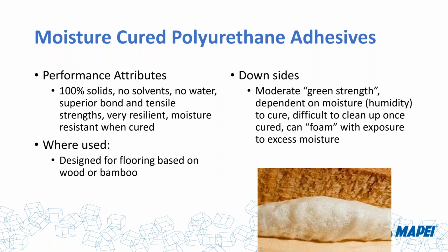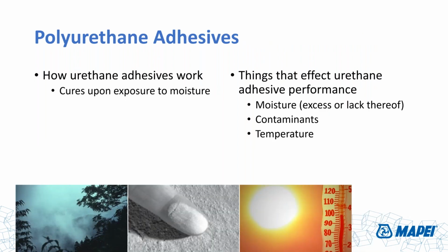When they put it into the adhesive bed, it foamed and actually lifted the marble up. So something to keep in mind when you're dealing with it. Again, they work by exposure to moisture. An open bucket is going to start the curing process. Getting it on the floor is going to start the curing process. You need to be advised about that. And the same things will affect its performance as well: moisture, contaminants, and temperature.